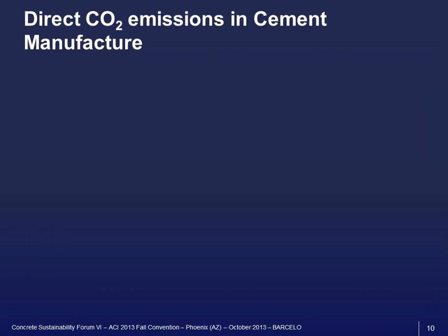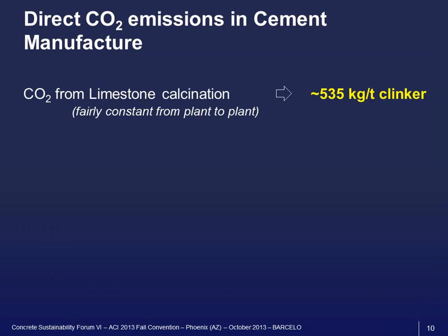So these CO2 emissions in cement manufacturing, where are they coming from? The first one is the CO2 from the calcination of limestone, so CaCO3 becoming CaO plus CO2. And it's about 535 kilograms of CO2 per ton of clinker. And this number is fairly constant from plant to plant.